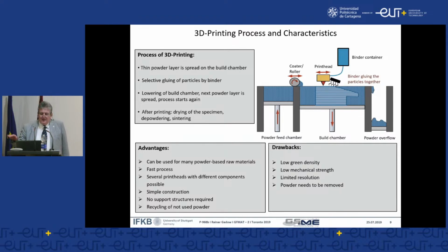And after this layer is finished, the machine moves downwards, and from the feeding chamber with a coater roller system, we fill it up with the raw material. Again, we have the projection, and so step by step we form the 3D geometry. The excess material is wiped out to the right-hand side, and normally these materials are recycled, so there is not much material loss. What we need in our case is a best fit of powder so that the powder flow behavior is appropriate to this type of processing.